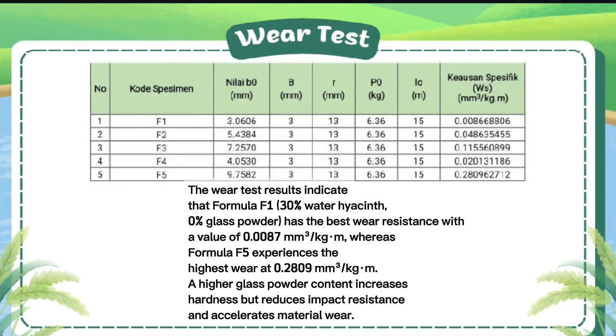0.01375 kJ. The wear test results indicate that formula F1, which is 30% water hyacinth and 0% glass powder, has the best wear resistance with a value of 0.0087 mm, whereas formula F5 experienced the highest wear at 0.2809 mm. A higher glass powder content increased hardness but reduced impact resistance and accelerated material wear.